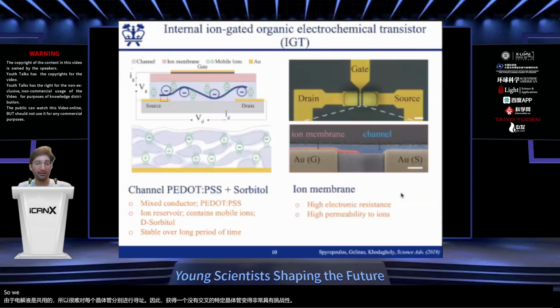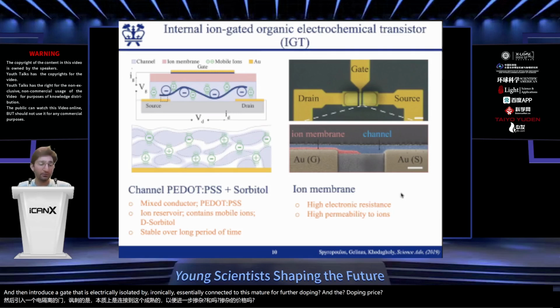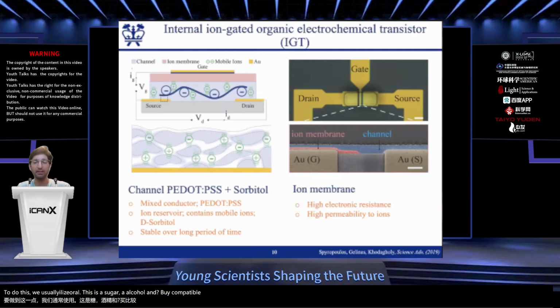So we hypothesized that perhaps if we were able to create a channel material that contains its own ions, we would be able to eliminate this and then introduce a gate that is electrically isolated but ionically connected to this material for further doping and de-doping processes. To do this, we utilized D-sorbitol. This is a sugar alcohol and biocompatible material, and we blended it with PSS, and it created water reservoirs that can embed ions from the PSS dispersion, mainly sodium ions, into the channel material. This way, we have local ions in the vicinity of our PEDOT:PSS rich regions.